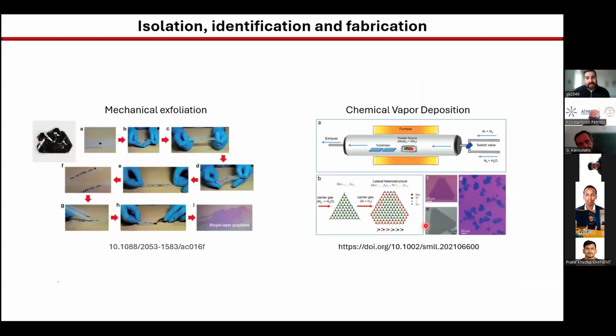Now, let's go further back and see how we actually isolate these materials. The most common and simplest way, and the way that Geim and Novoselov used, was the typical Scotch tape thing. This is mechanical exfoliation. You have a bulk crystal, you put it on a Scotch tape and you spread it all around to thin it down. And once you do that, you stamp it, you just stick it on the substrate of your choice, and you spend some time under an optical microscope to find the monolayer. Of course, in this situation, you will end up having a lot of other flakes on the same substrate that are of no use. A more controlled way is chemical vapor deposition, where you can chemically grow the monolayers.